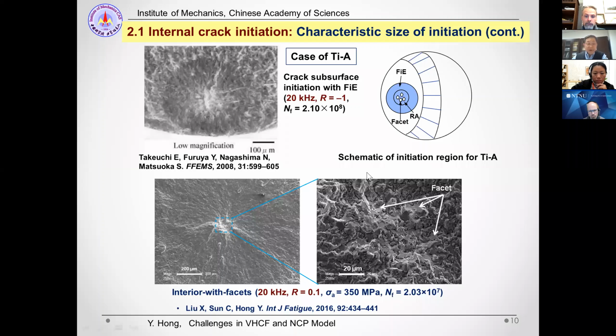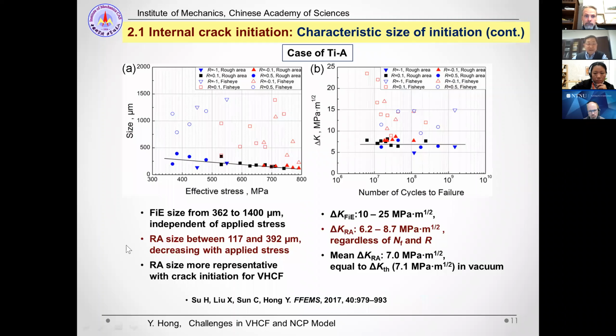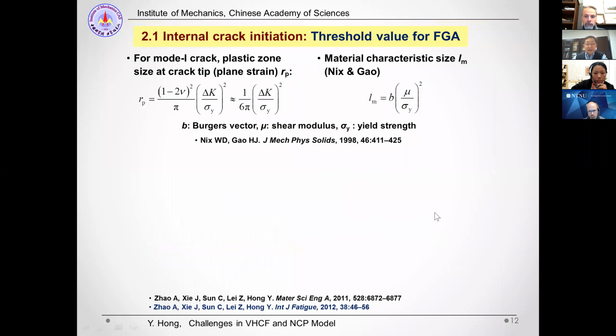Again, we also measure the RA size, and it's between about 120 and 390 microns. It is also quite stable in comparison with the fisheye size, which is a large range, and also the delta K value is stable for titanium alloys. So we try to analyze the threshold value for the crack initiation region.